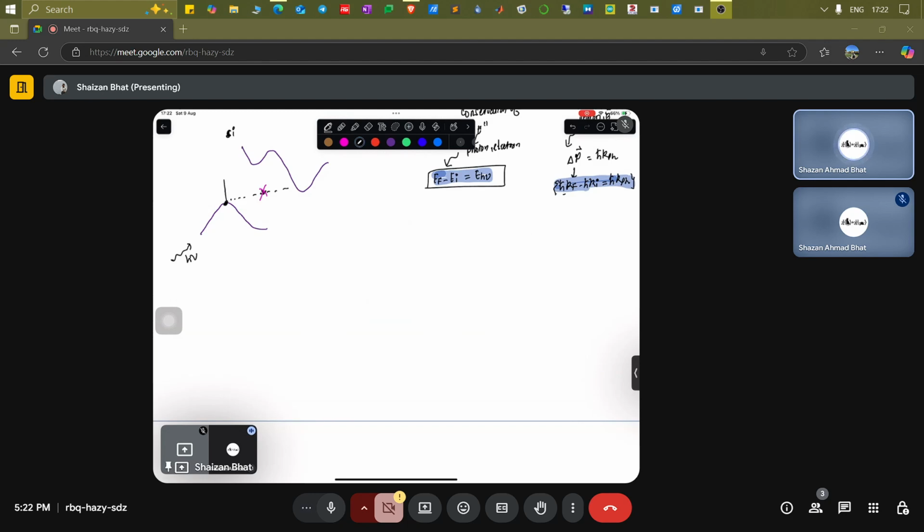The photon is going to go up, then a certain intermediate process is going to happen, and then this is going to reach over to this place, which is the conduction band minimum. Let's say, for example, a phonon has the ability to take it to the other minimum of the conduction band. So this is like a phonon mediated process. That's why it's not an efficient process. The absorption is not efficient.